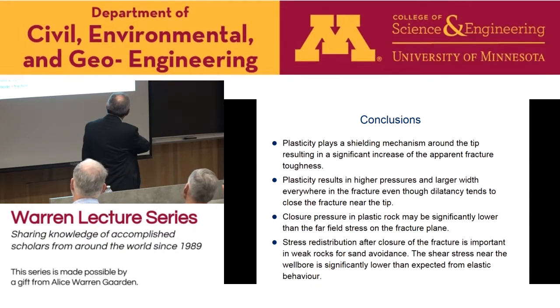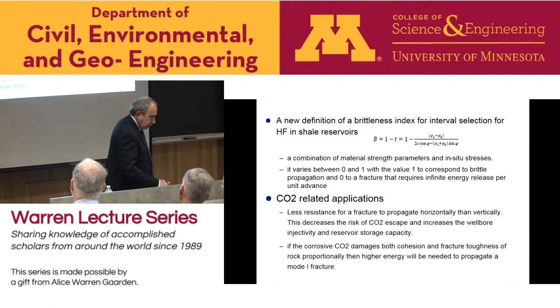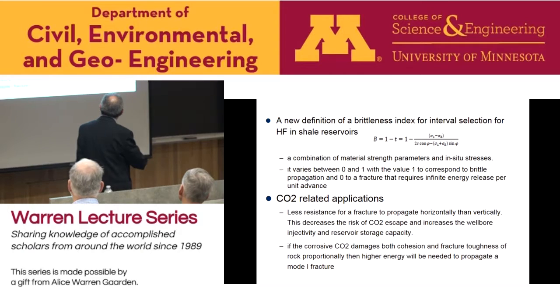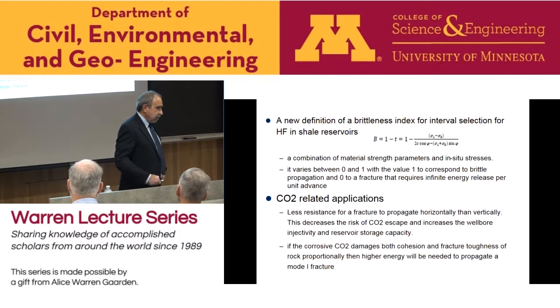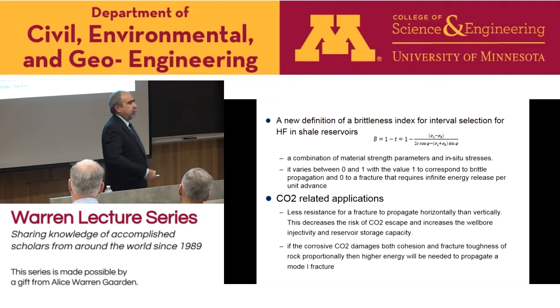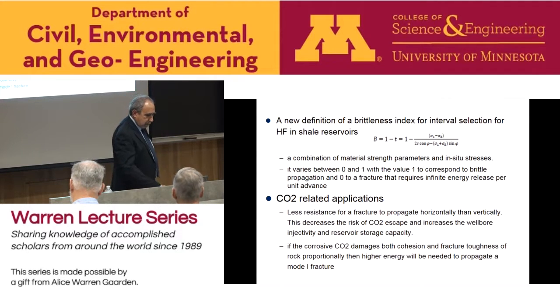This was the introduction of this brittleness index, which was introduced for selecting intervals to do hydraulic fracturing. And for the CO2-related application, it is more likely that the fracture will propagate horizontally than vertically. If the fracture propagates horizontally, we'll have some benefits to increase the injectivity and storage capacity. And of course, if CO2 damages both cohesion and fracture toughness proportionally, then we need higher energy to propagate a mode 1 fracture. Mode 2 or mixed mode is still under investigation. And definitely it's not the full story here. We need more work to look at this issue. This is just first suggestions.